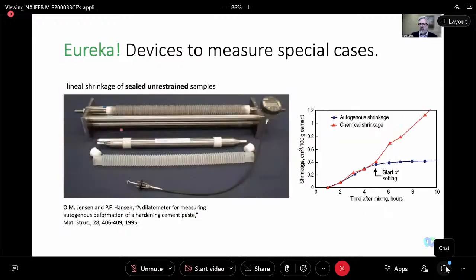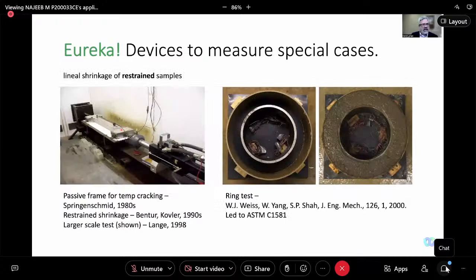So we can let the machine control the test with strain. So the point of this is that as the material shrinks, we want to measure how much is the net stress, how much force is created, and then we can apply more stress to lengthen it as happens in a restrained sample. So this study allows us to think about how to characterize shrinking concrete and what is the early age cracking problem.